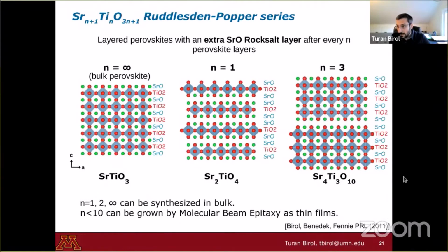Now, what I had done in this field back in, this is last decade, 2011, was to study the ferroelectric properties of a new class of materials. So strontium titanate is a very well-studied perovskite. So it has this crystal structure with alternate strontium oxide and titanium dioxide layers. And one can imagine building other types of layered perovskites by adding a double SrO layer into the crystal structure. So this gives rise to the so-called Ruddlesden-Popper series with this chemical formula with different values of n.